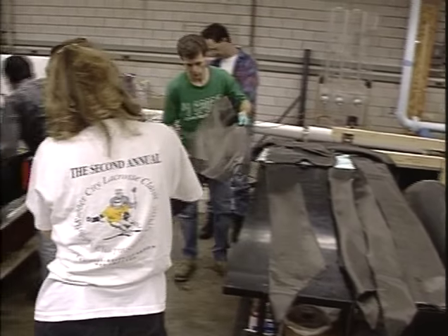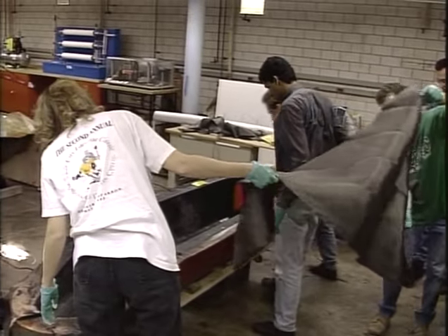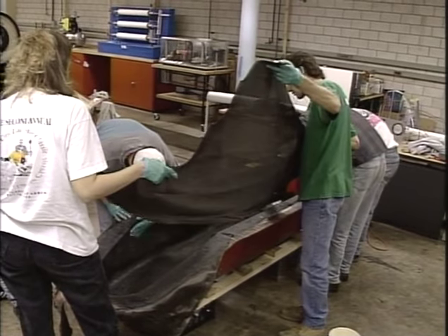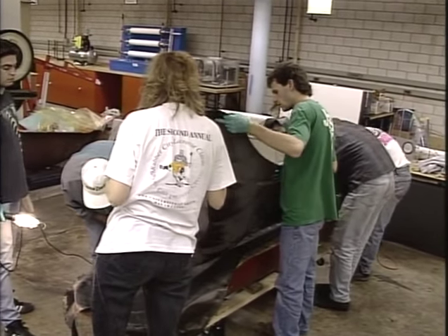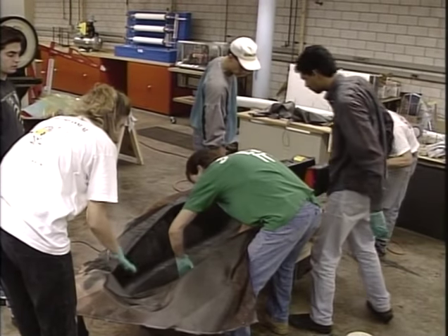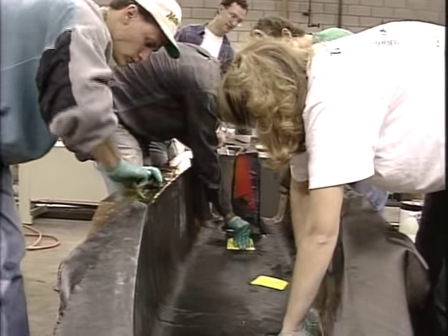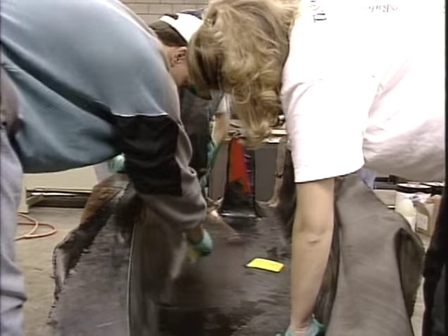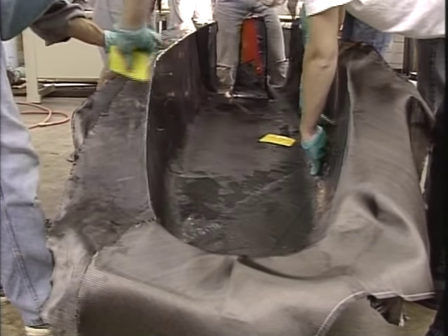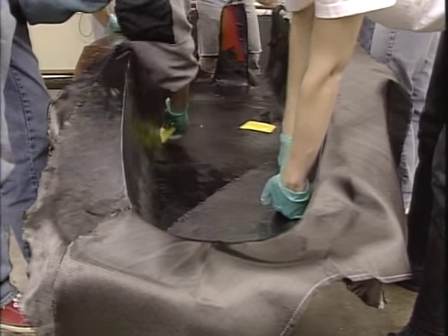We are still interested in time and want to move as quickly as possible without leaving any air pockets, dry spots, or excess resin. We also do not want to pull out excess fibers from the cut edges of the graphite, as fabrics want to shred when cut and the problem gets worse when wet. We have to work carefully at seam areas to make sure loose fibers are not skewing the fiber orientation or causing air pockets. We could add triangular pieces to complete the 45-degree ply as soon as the large piece was completely smooth. When resin was applied to this layer, it was applied more carefully and more sparingly in the spliced areas.